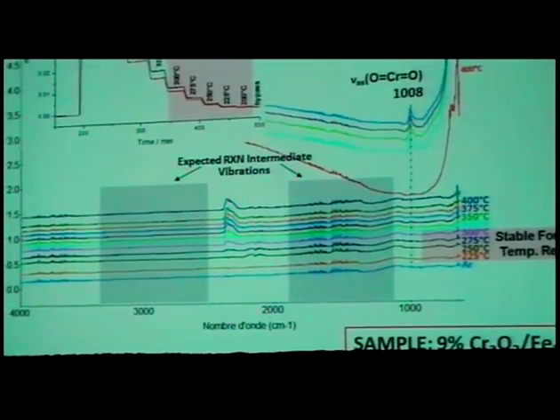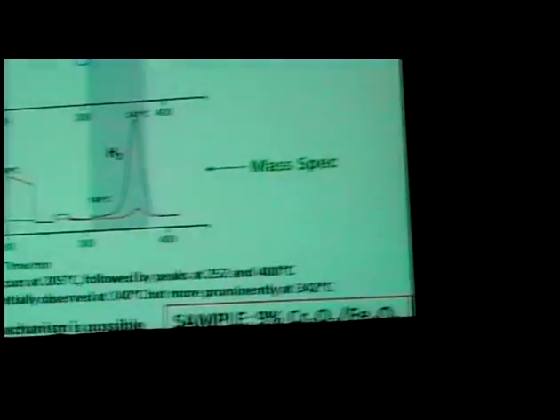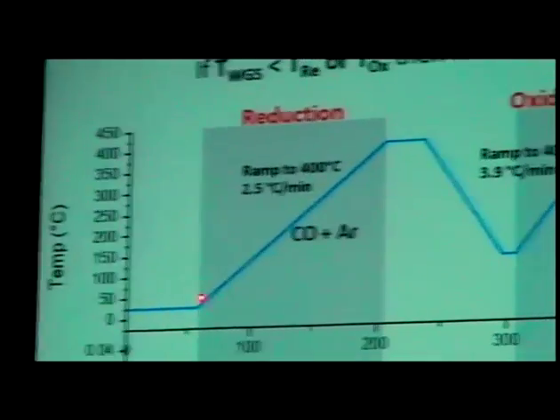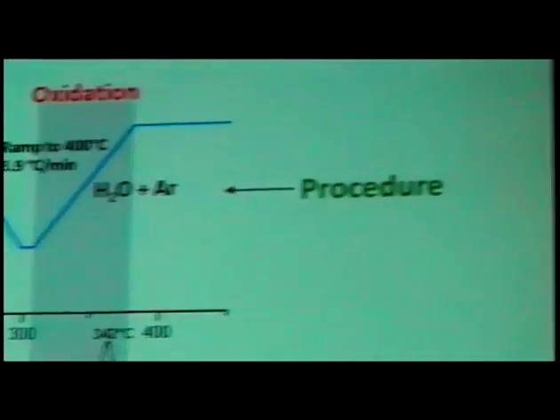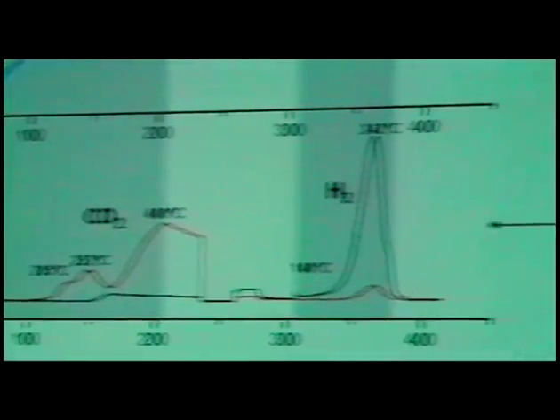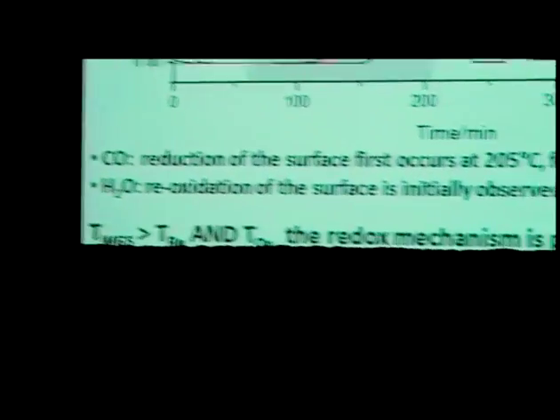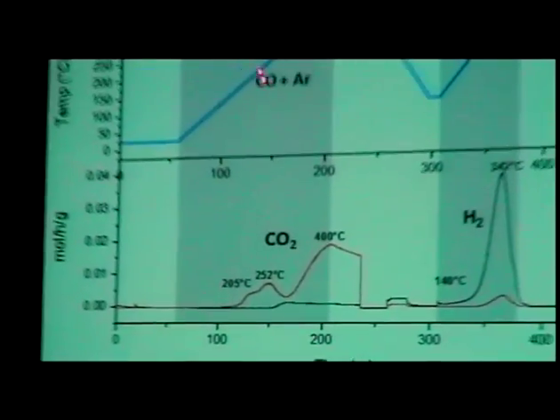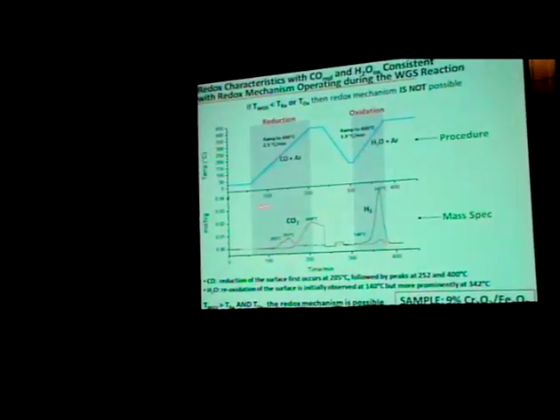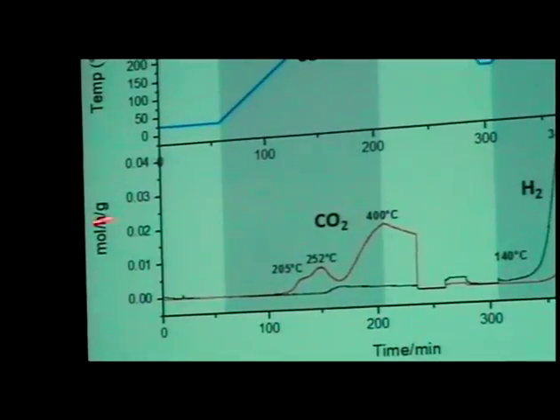So then we turn our attention to the other mechanism, which is the redox. And so we did the following experiment. It's a temperature program experiment. First, we heated the catalyst in CO and argon, using CO as a reducing agent to make CO2. And this is the result in the mass spectrometer from this temperature program reaction study. And you can see that indeed, at very low temperatures, 205 degrees to 252, even 400, you're making CO2. In other words, CO is able to extract oxygen at very low temperatures. And remember, this is the region where formate would have been stable had it been formed.